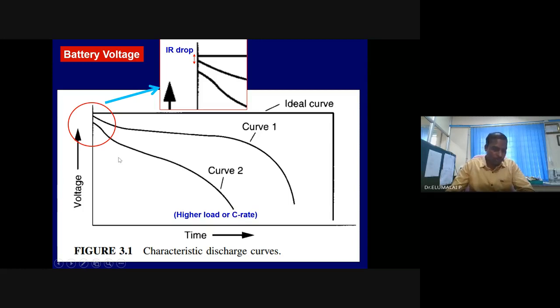Here the take home point from this slide is, this is a discharge profile, which is voltage versus time. An ideal battery is expected to deliver the constant potential, plateau potential, until all the charges are exhausted. Once the charges are exhausted, extracted or discharged, it should drain to zero. But there are no ideal batteries; they have plateau potentials and sloping potentials during the discharge. Depending on the load, you have a reduction in the capacity or reduction in the discharge time. Instead of 8 hours, it works for 1 hour, or 4 hours, 5 hours, less than this. There is a reduction in the capacity.